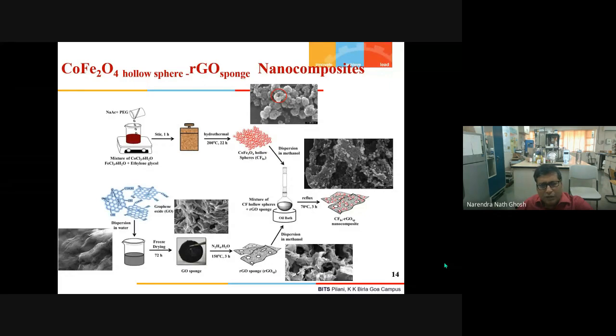Then we disperse this RGO sponge in a round-bottom flask. We add this cobalt ferrite, we mix them well, we reflux it, and then just by applying an external magnet, we can remove them, and you can see that on the surface of the RGO sponge, these nanoparticles of cobalt ferrite are anchored.